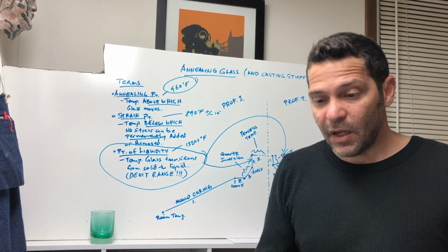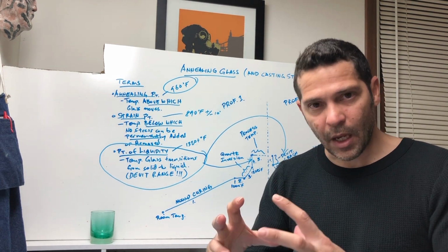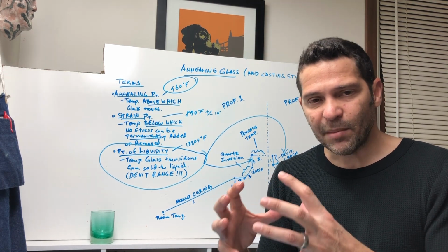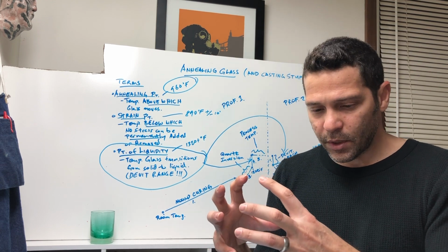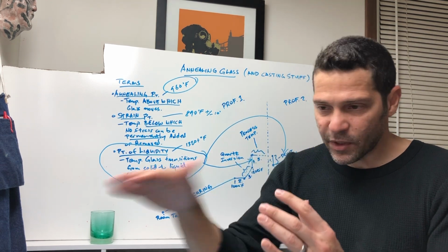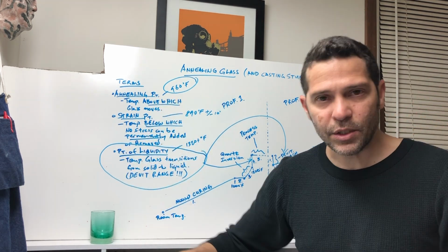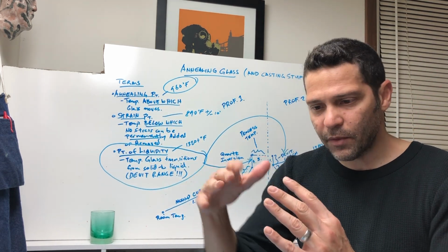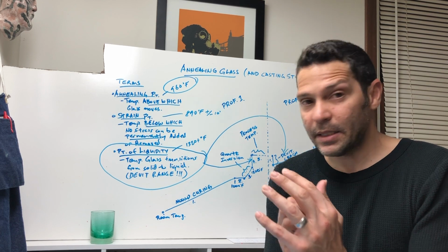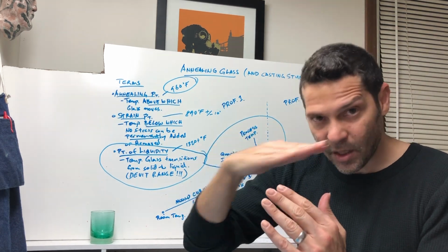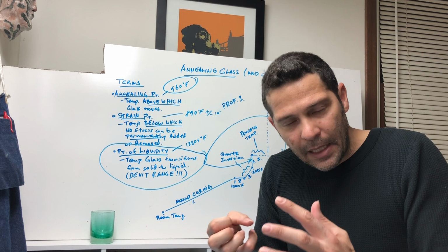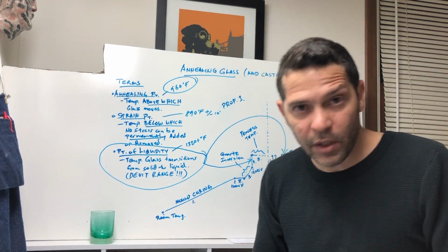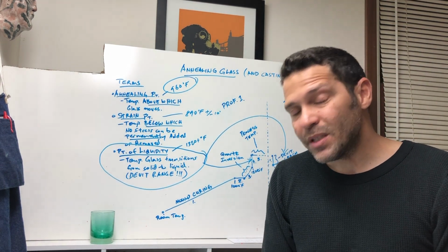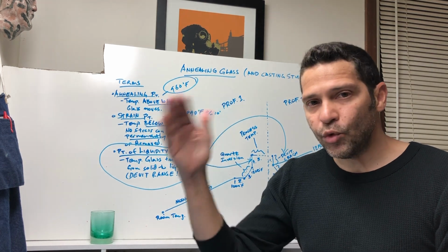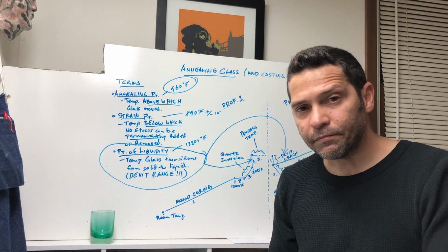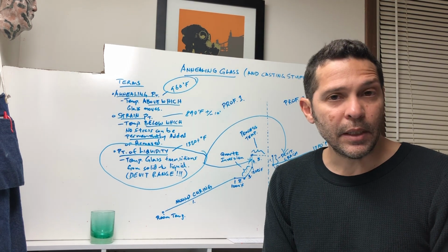First is, if it's a closed mold that is surrounding an object, I need to think about shrinkage. If that mold is insulating that glass, the surface of it would freeze because I crashed the kiln and it's getting really cold. The surface might freeze, but the interior stays hot. And it still has to shrink, but it can't pull from the top because the top's frozen. So it's gonna suck in, and you get suckers. You get shrinkage. That happens specifically because you cool down too quickly from your working temperature to your annealing temperature.